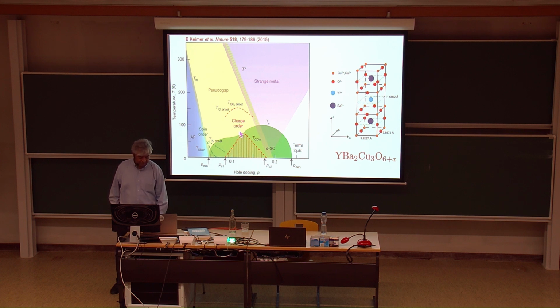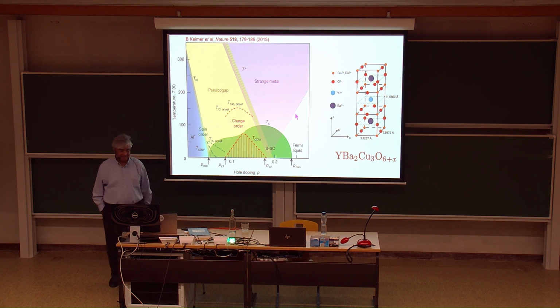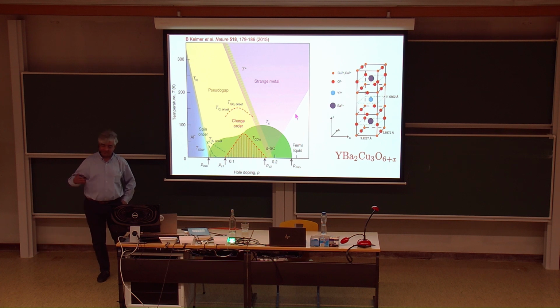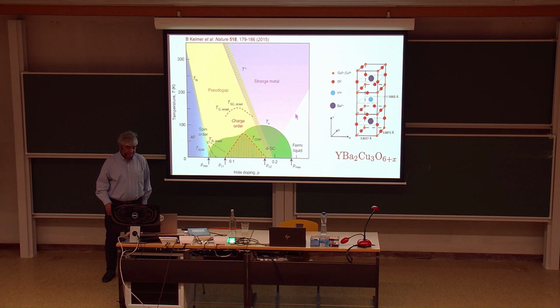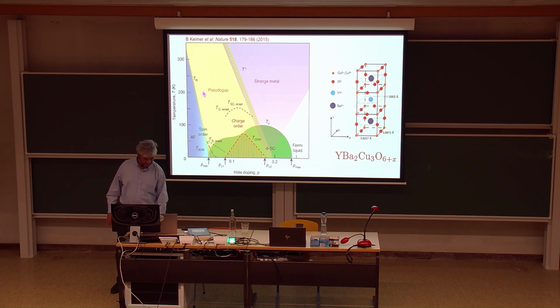But the focus of my talk mostly will be on what happens above Tc. Now, if you took almost any superconductor, including many of the new ones, and you went above Tc, things become very familiar. You can describe it by Fermi liquid theory, density functional theory. It gives you essentially a complete description of the normal state, if not of the Tc. And here, the dramatic thing is that does not happen at all. And so really the focus of my talk will be to talk about the pseudogap phase, which I'm now going to say a little bit more about.